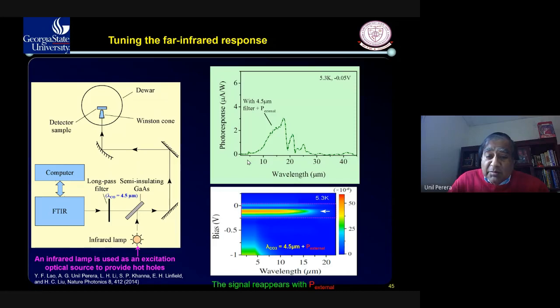So we came up with the option to say, how can we avoid that? So this method avoids the threshold limitation due to the reduction of energy gap. Energy gap is much higher, which is matching 3 micron, but we can get to very long wavelength micron. In fact, we measured the dark current and fitted that, and so this work is published in Nature Photonics, and in fact, on the cover, they highlighted our work and also had a discussion with the editor on that. So this is something we called a hot hole detector, extending the threshold beyond the standard threshold. Again, this is an unexpected result. And in fact, Divya worked on some of this work.